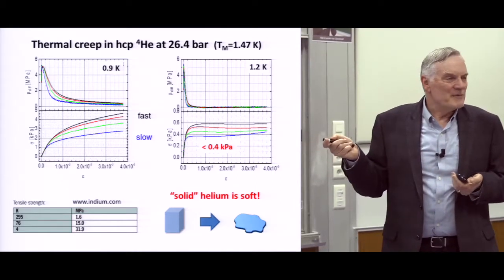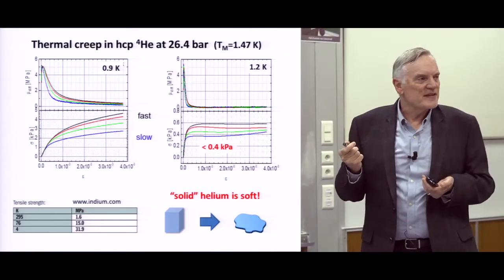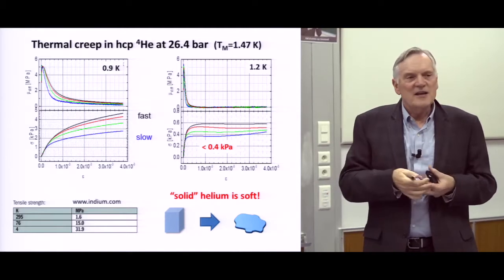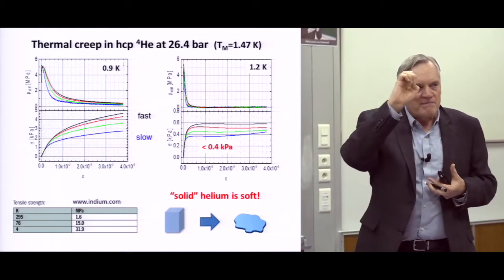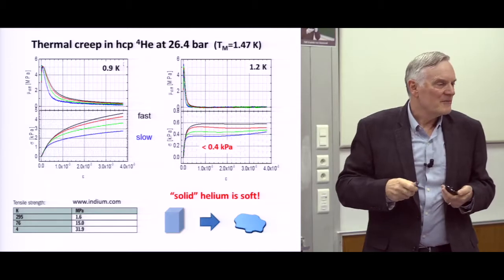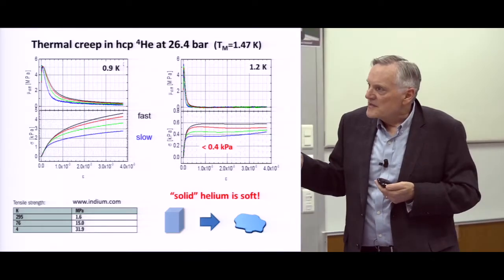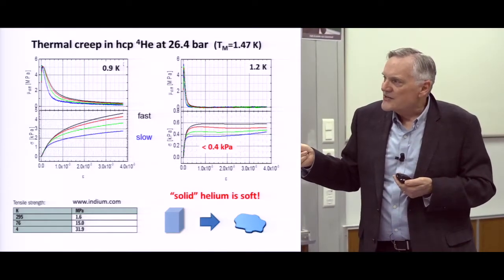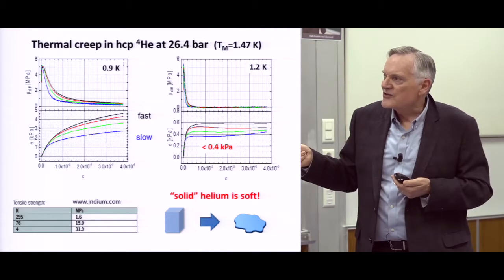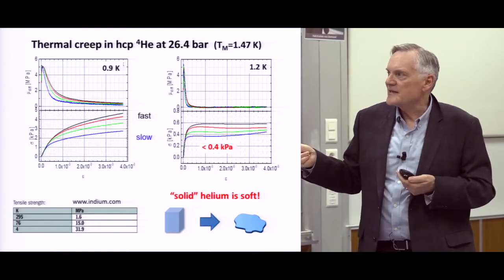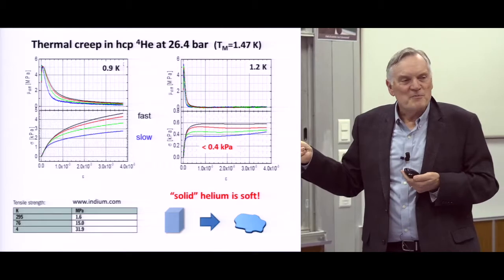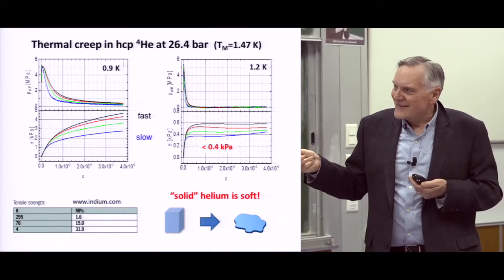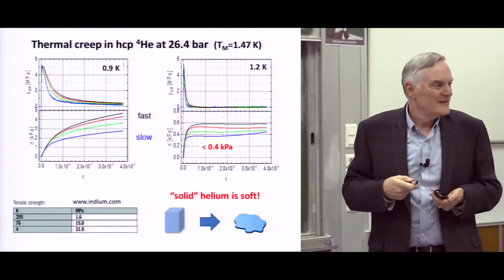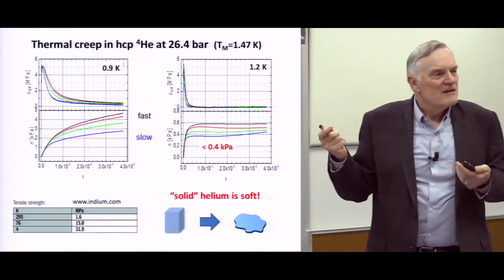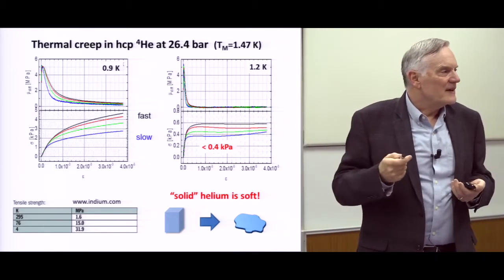But in labs, people who think of a soft metal that flows think of indium as one of the softer metals. If you take a wire of it, you can cut it off with your fingers. It's not a problem. It's soft. Indium's tensile strength at room temperature is measured in megapascals. It's a few megapascals. As I said, this could be a few pascals. So it really is, I don't know, 10,000, 100,000 times more ductile or softer than indium